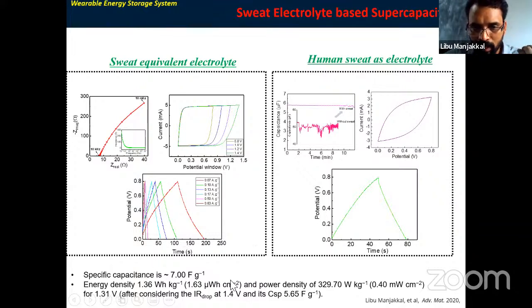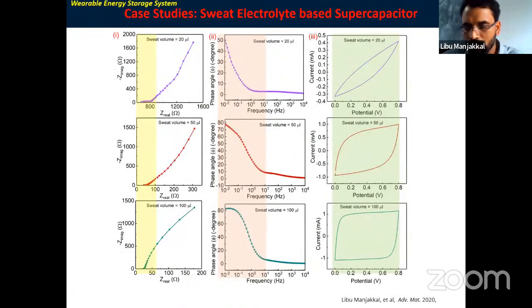And when I compared the sweat equivalent electrolyte with the human sweat, it shows almost 7 farad per gram capacitance, and that is enough to operate small sensors. And then there will be a question: different people have different volumes of sweat or physical exercise. Then I found that it purely depends on the volume of sweat and the area of the device. Then I compared different volumes of sweat in impedance spectroscopic analysis and also CV analysis, and also charging discharging.